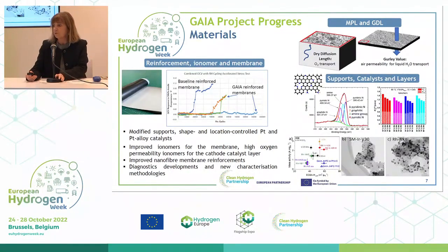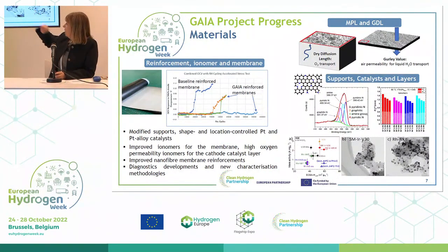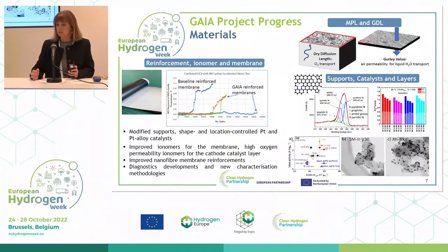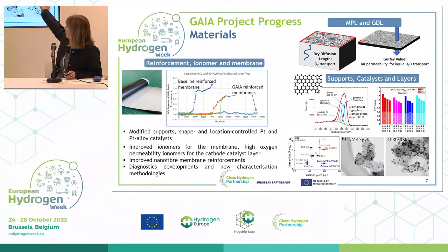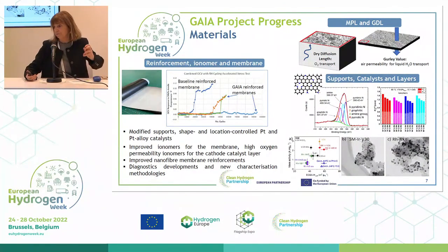Okay, let's move on. So project progress, I'm not going to go through everything that was developed in terms of the materials, but you can see just from those examples that are given up there, a lot of work was done on modifying supports, in terms of the catalyst itself. So shape-controlled catalysts, as an example down on the bottom there, of work on octahedral shaped catalysts. Particular shapes give very high activity, on locating the platinum within the support, in the porosity, external to the porosity, on the development of high oxygen permeability ionomers. Those are the lines that are given there, determining the oxygen permeability of those various ionomers, and also on the diffusion media, the MPL and the GDL.